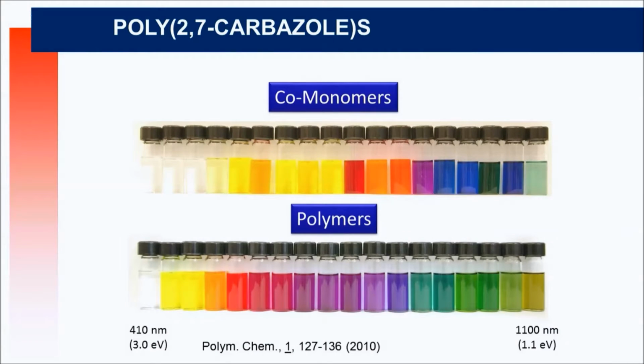So that's an example. The carbazole monomer is transparent. If you make the homopolymer, the band gap is around 3 electron volts. So it's not useful for solar cell application. If you copolymerize carbazole with different electron-poor units, you can tune the band gap from 1.1 up to 3 eV. So you can make the material you want or the color you want with the band gap you want. It's quite easy. One single student can make all those polymers within a few months, let's say.